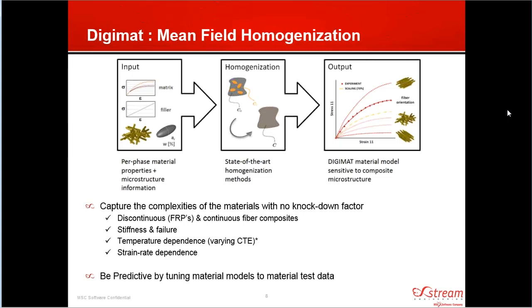And what that means is that we're going to have a description of what the fiber orientations are, how aligned they are, how random they are, in what direction. We're going to have a description of how long the fibers are, so the aspect ratio. And we're also going to have a description of how many fibers there are for how much plastic, so what's the volume fraction of fibers relative to the plastic. From there, we can homogenize all those different properties together to predict what the composite response is.